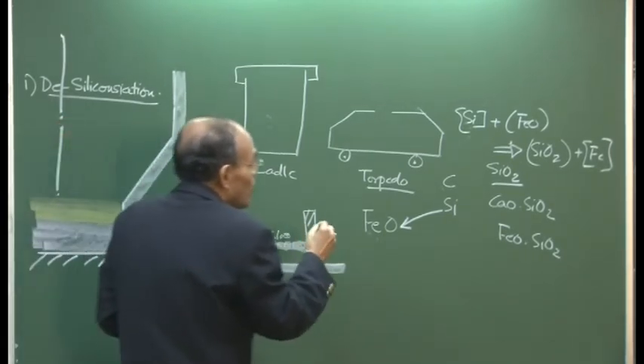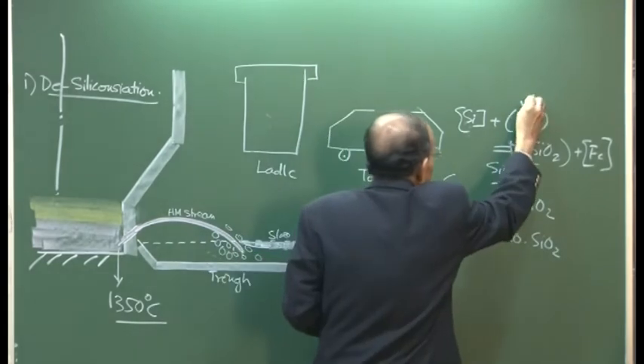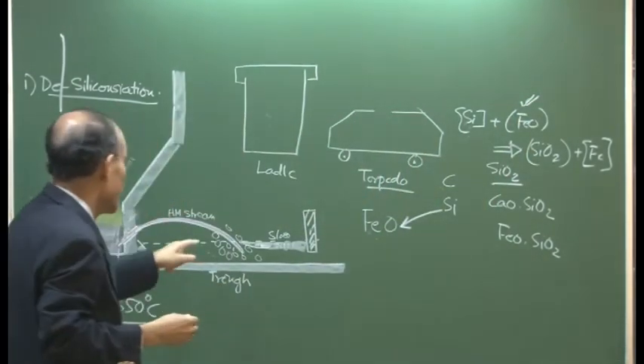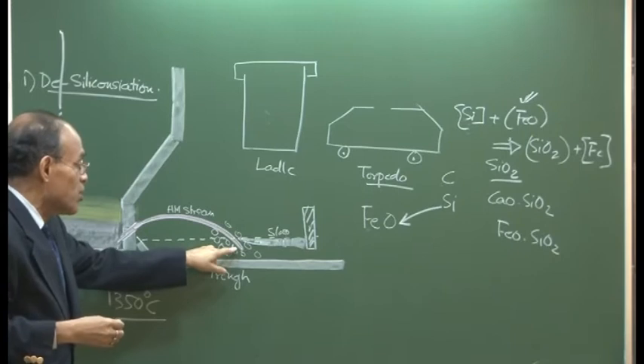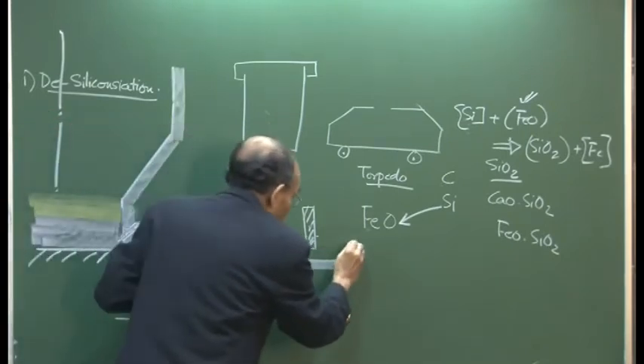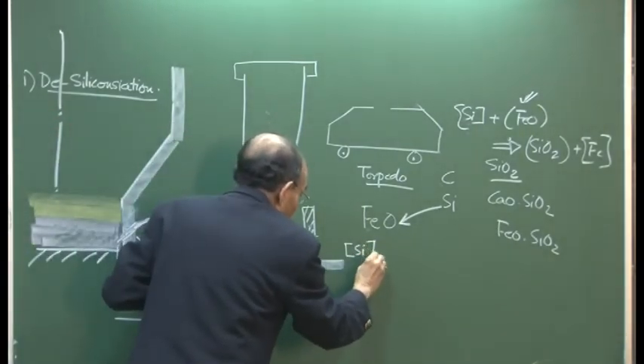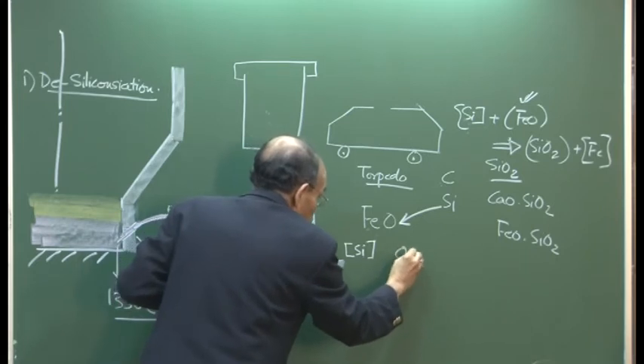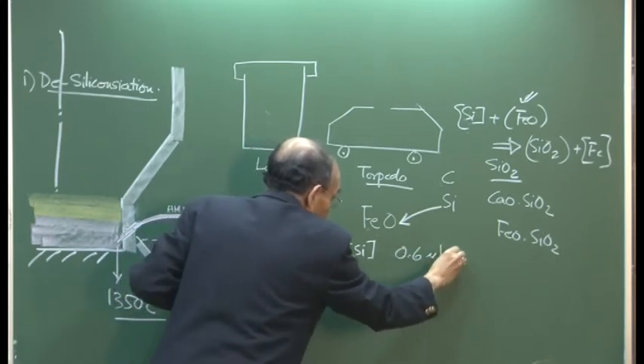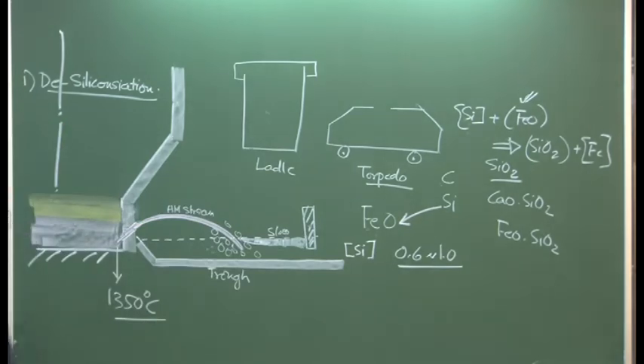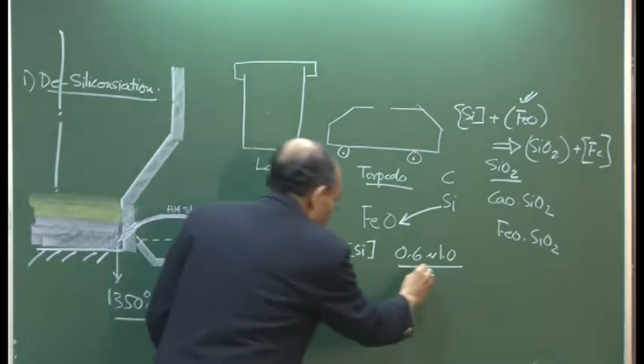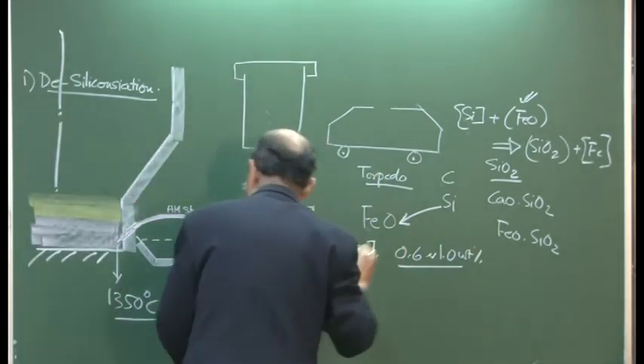We have to just regulate how much mill scale we have to add, what should be the rate of addition of the mill scale into this region, such that this hot metal silicon which comes out is in the favorable range, and that favorable range is within 0.6 and 1.0 weight percentage.